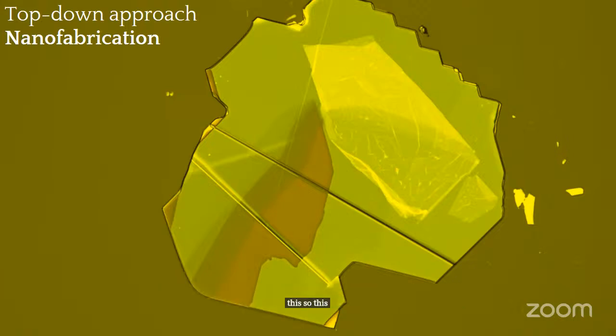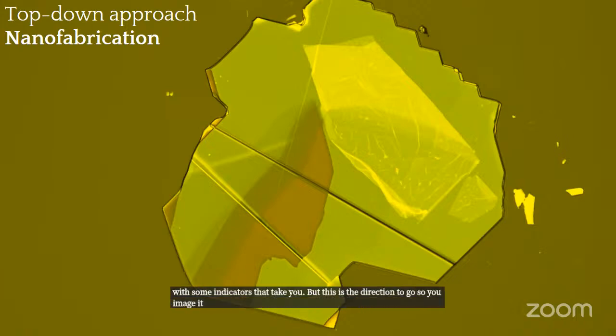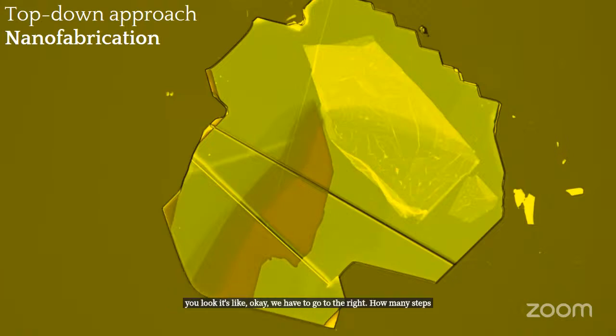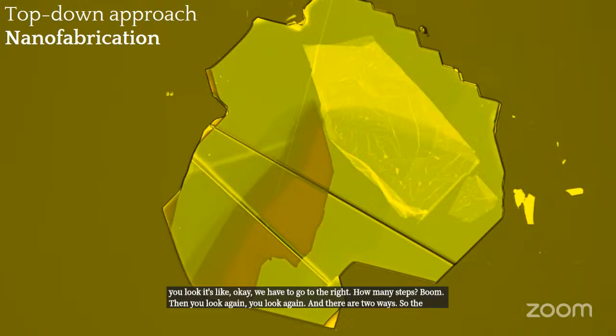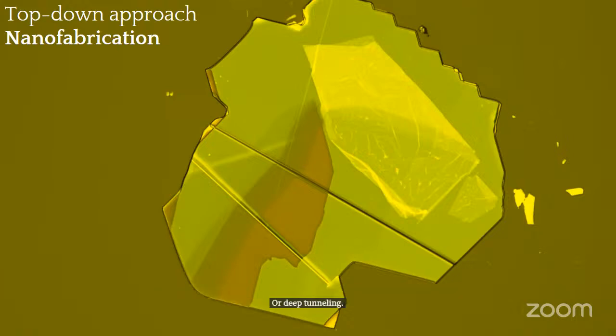So this has to be located in a very precise location in the substrate with some indicators that tell you, this is the direction to go. So you image it, you look, and it's like, okay, we have to go to the right. How many steps? Boom. Then you look again. And there are 2 ways: the capacitive imaging or the tunneling. Tunneling is nice, but it probably takes longer, but it's safer. So we are trying to develop both possibilities to eventually do it. It has been done. It's not new. People have done this for 10 years already. Not many people, but people can do it.